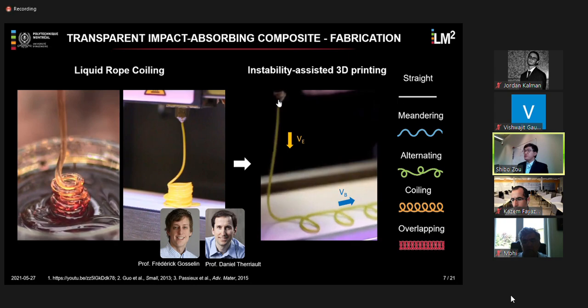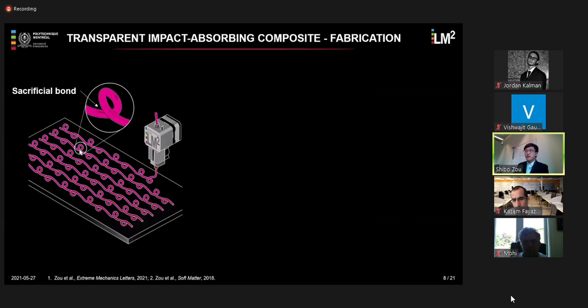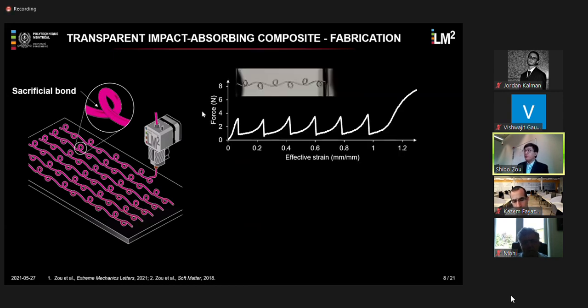And because the material is also cooling down during this deposition process, at the intersections along the fiber, a weakly fused bond will be created. And these weakly fused bonds will actually act as sacrificial bonds upon mechanical loading, as you can see here. Under tension, the sacrificial bonds will be broken one by one and release these hidden lengths along the fiber. And this gives us extra peaks on the force displacement curve shown here. And the area under the force displacement curve represents the amount of energy absorbed by the system. And this gives us this toughness enhancement.